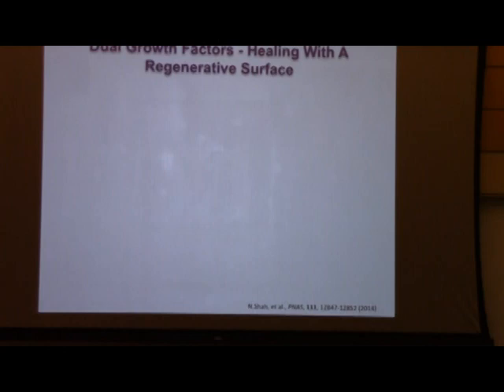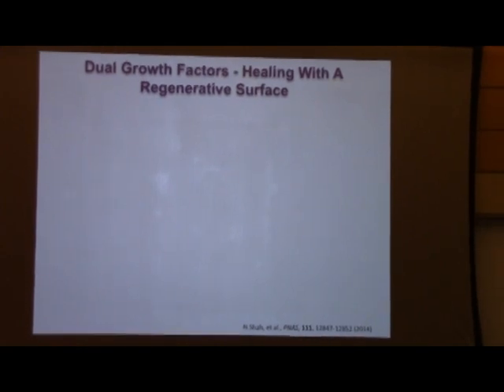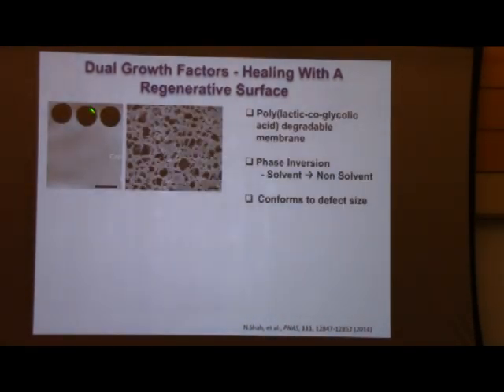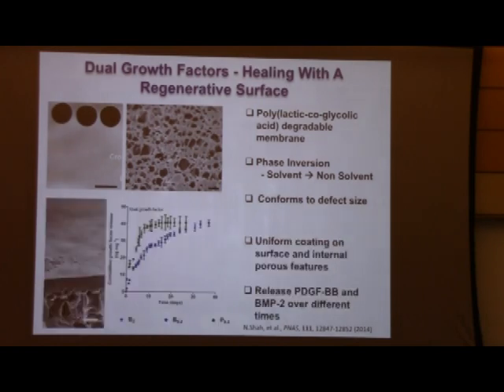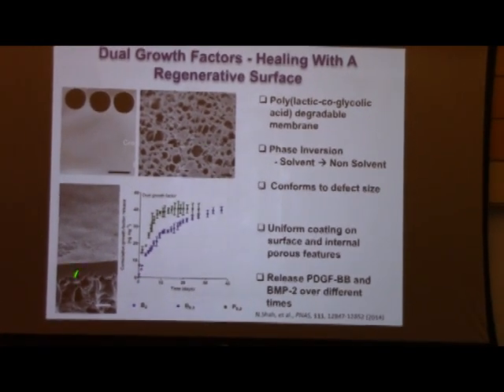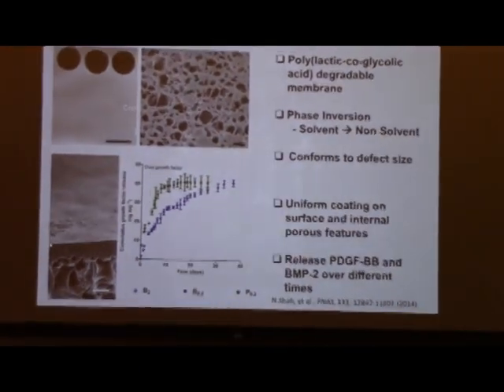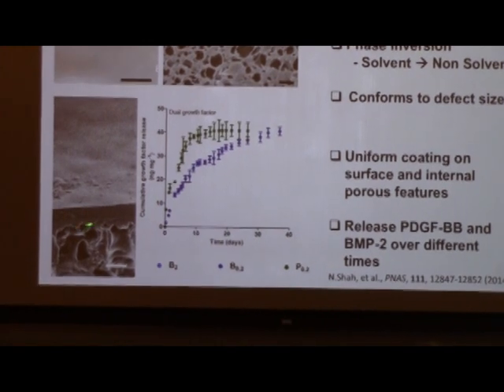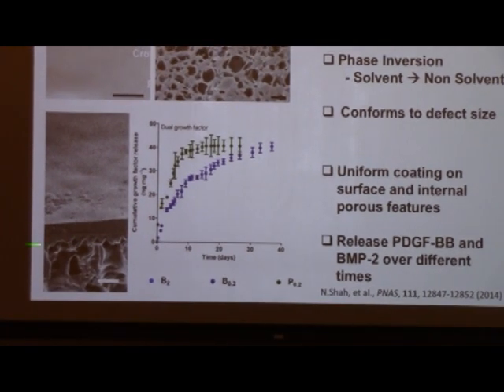What we'd like to do is replace that kind of graft surgery with a much simpler approach by generating first a degradable membrane, and we'll use a familiar polymer like the polylactic glycolic acid polyester that I described before, and we'll process that polymer so that it's very porous, and we get these little foamy inserts. They're a thin foam insert that degrades over time. We'll take that known polymer and then coat it with our layer by layer film. So down at the bottom, you can see that that porous membrane now has a little top coat. This is a side view. You can see the top of the film here, and in the cutaway, you can see that it's sitting on top of this porous membrane.